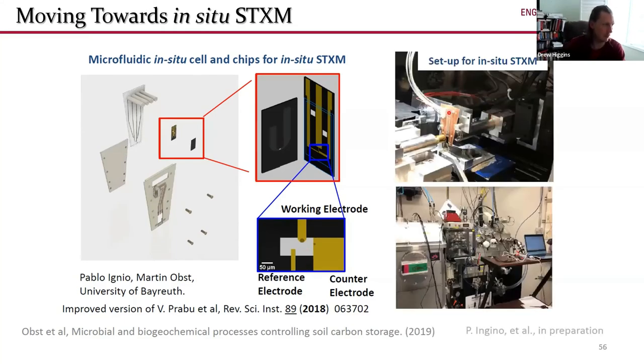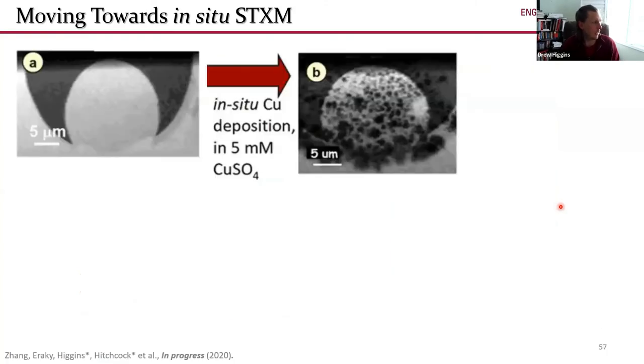We just take this device, we insert it into the STXM chamber over at Canadian Light Source, and we can do some in situ measurements on electrochemical CO2 reduction catalysts under electrochemical CO2 reduction conditions. And so as a proof of concept, Chunyang, Adam, and friends have worked very hard on the first thing to do, making sure that we can achieve electrochemical CO2 reduction conditions and actually look at a catalyst. And so we use electro-deposited copper as our entry point for doing these measurements.